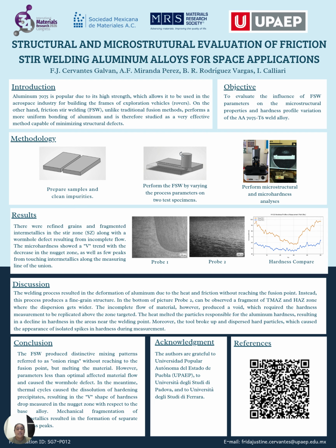targeted. The heat melted the particles responsible for the aluminum hardness, resulting in a decline in hardness in the areas near the welding point. Moreover, the tool broke up and dispersed hard particles, which caused the appearances of isolated spikes in hardness during measurement.